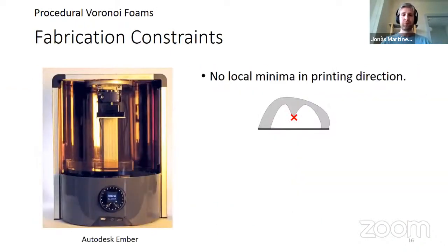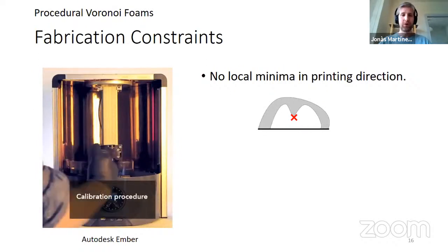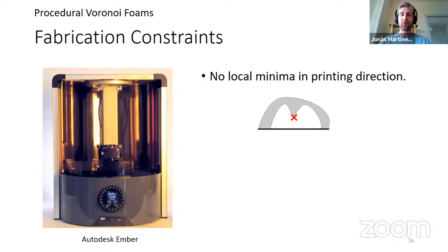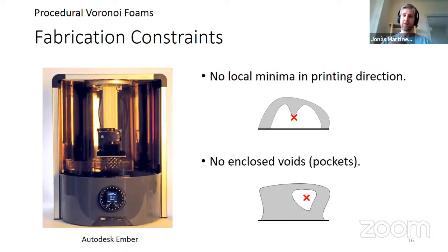So let's dive first into the first work. What we wanted to do is an isotropic material that we could print with an Autodesk Ember, which is this kind of stereolithography machine. The fabrication constraints here are that you need to have no local minima in the printing direction, so you cannot have these kinds of islands. And also, you cannot have enclosed voids because they will trap the resin in the interior, and that's something you want to avoid.